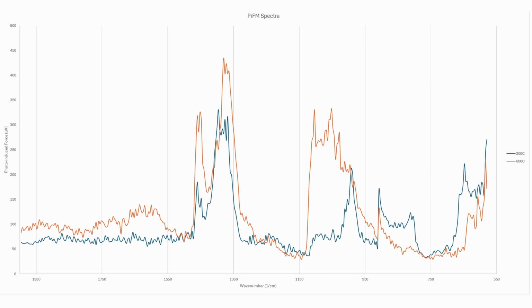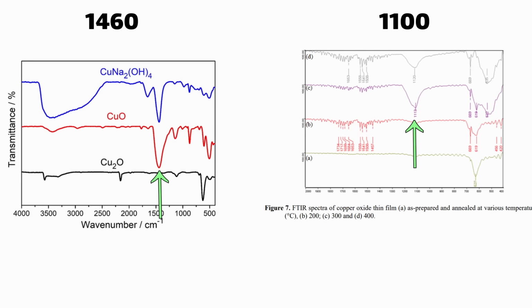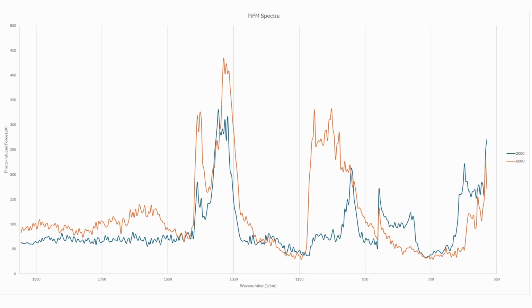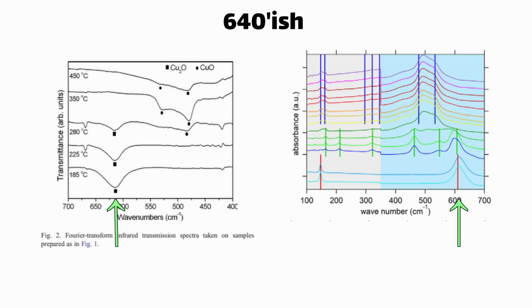If we look at the IR spectra, we can see some differences as well. The 600 degree sample has an increase around 1460 and 1100, which according to reference IR spectra correlates with copper 2 oxide. And in contrast, the 200 degree sample has more signal around 640, which is indicative of copper 1 oxide.